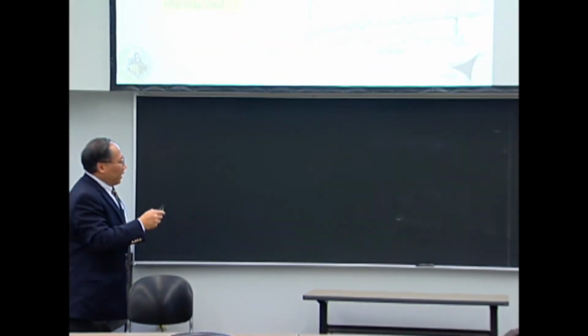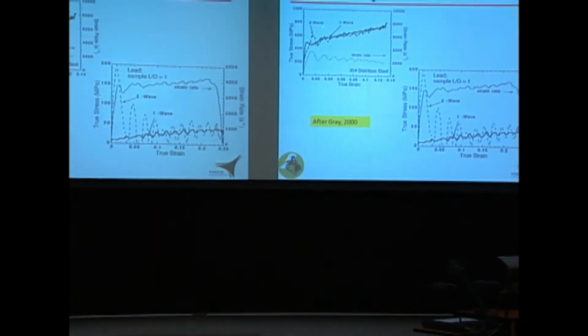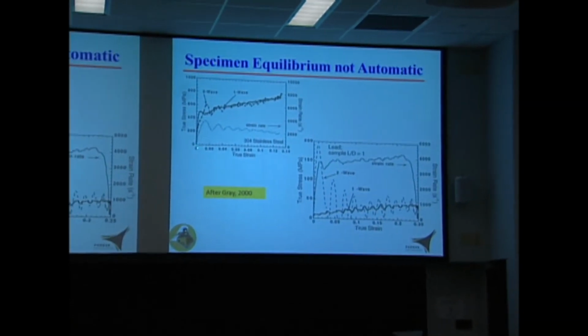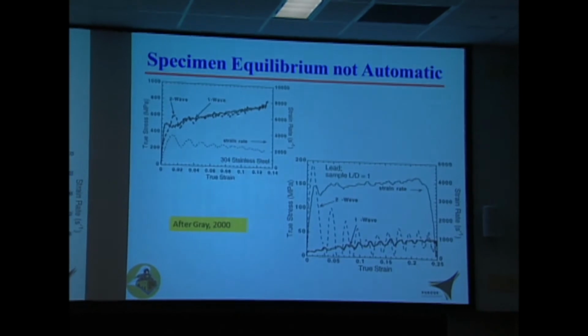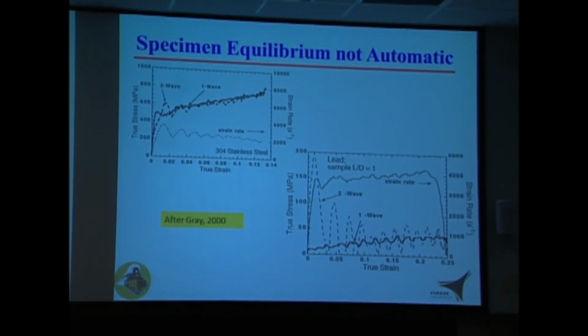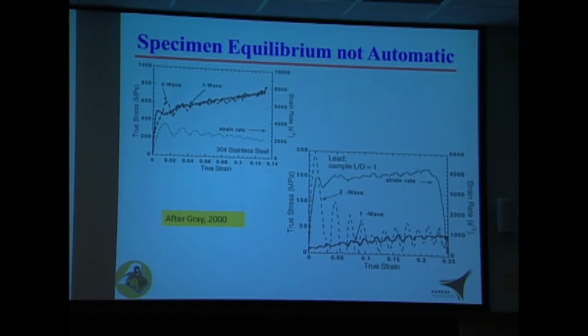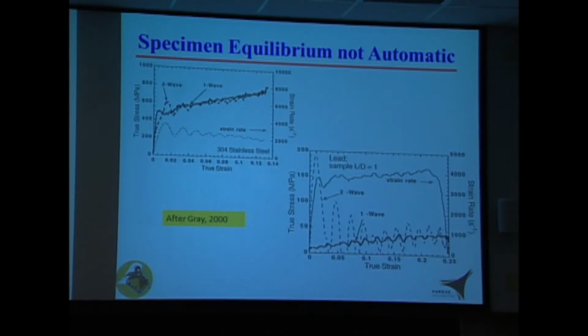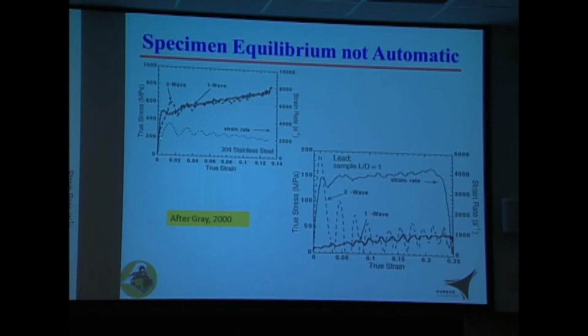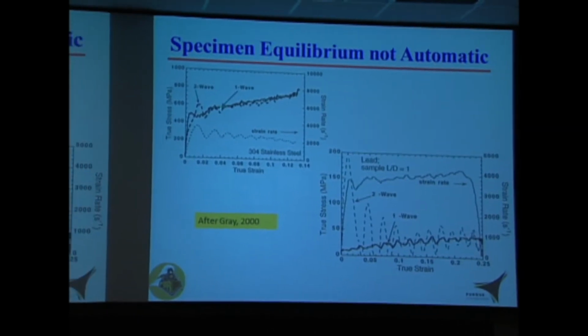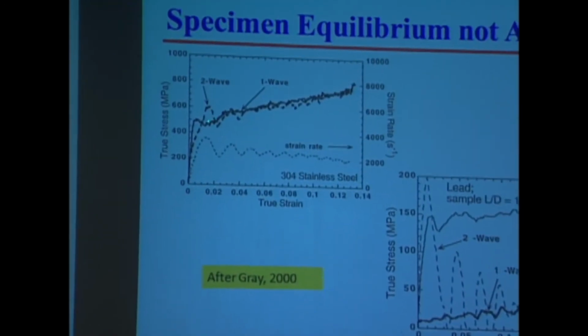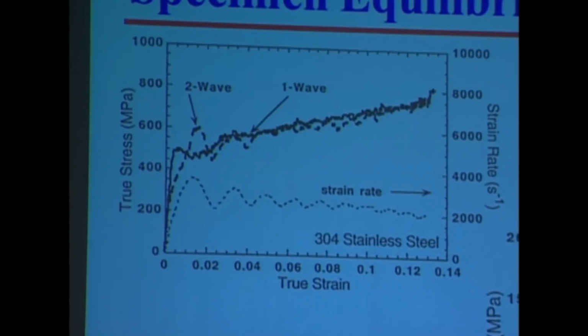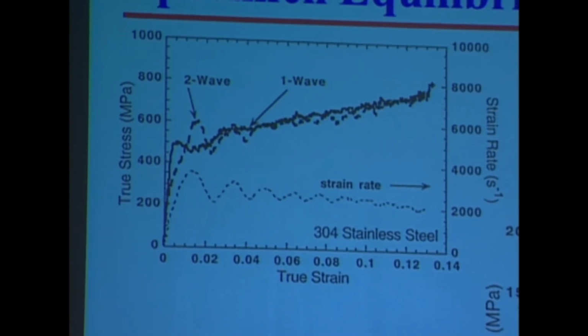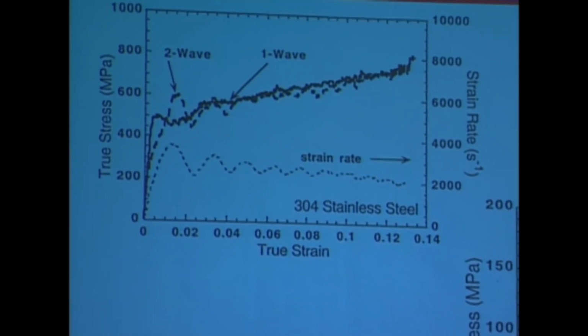So here's an example. I was measuring the stress strain curves. If I have a piece of stainless steel, in mechanics you plot basically the load deformation history. But I can plot the load from the front end. Remember, my sample has 2 ends. Once the front gets hit, the back end transmits the load out. If I measure the force from the front end or the back end, you see they reasonably overlap each other. So the load in the sample is reasonably evenly distributed. Front end, back end is very similar.